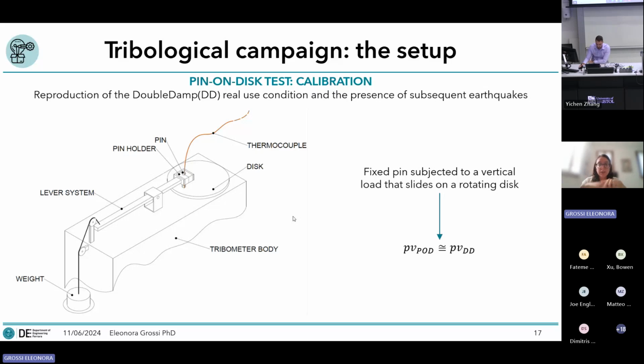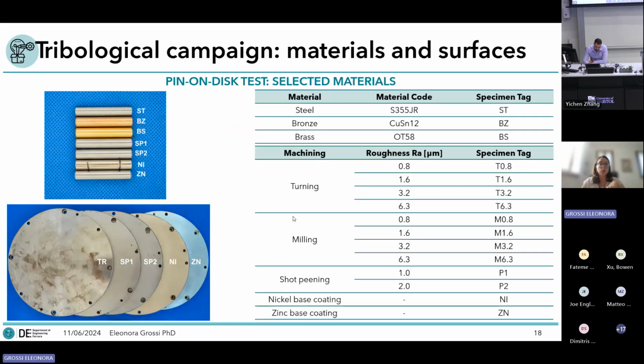However, this type of test can be considered as a scale test. So the pressure applied on the pin and the velocity of the disc must be set so the product between pressure and velocity of this test should be similar to what I expect on my friction interface in a real use condition. So at this point, once I set the pressure and velocity, I just needed to select materials and finishing. So for the pins, I selected 3 different materials: steel, because the device is made of steel, bronze, and brass, which are softer than steel.